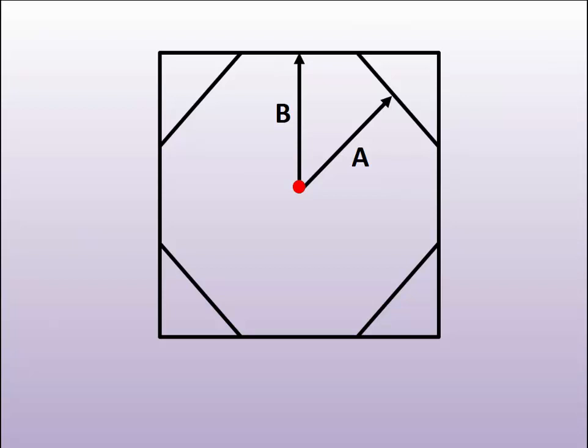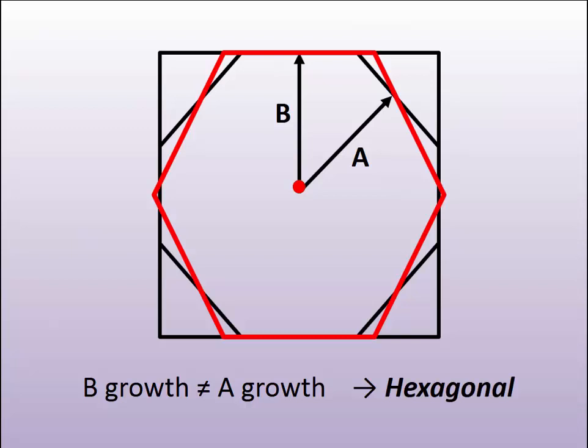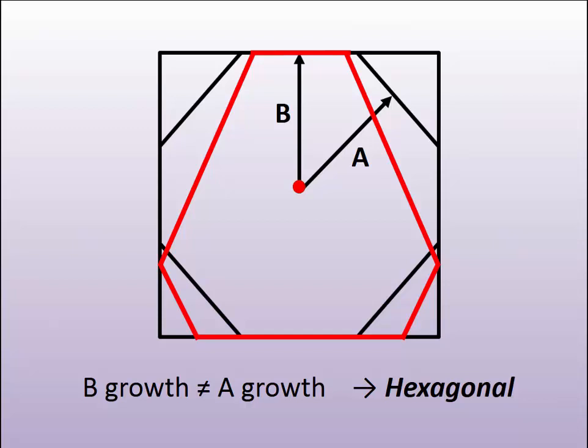If there is not such an equal growth amongst the two faces, I may end up with only a hexagonally shaped crystal. Or maybe it has growth that is faster on three sides, but not one. So I get preferential growth, for example, on the 2, 0, 0 faces. But my 1, 1, 1 is just hanging in there, giving me these clipped corners, if you will. And this is how I get that very characteristic hexagonal shape, where there's three equal long sides and three equal short sides that make up the grain.